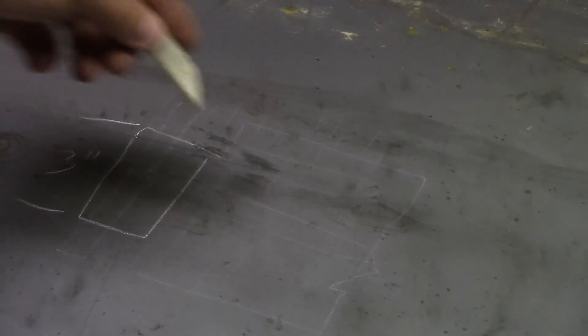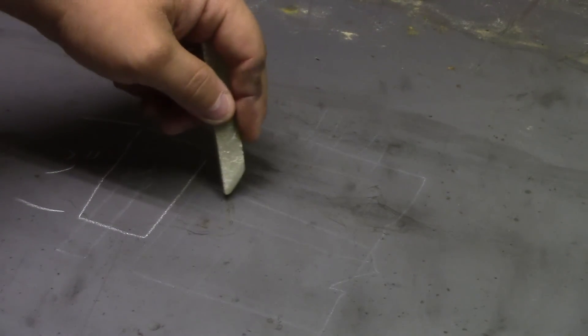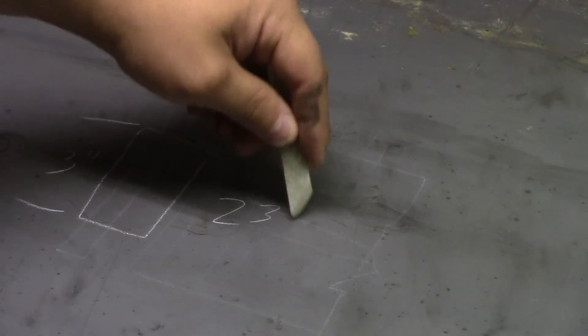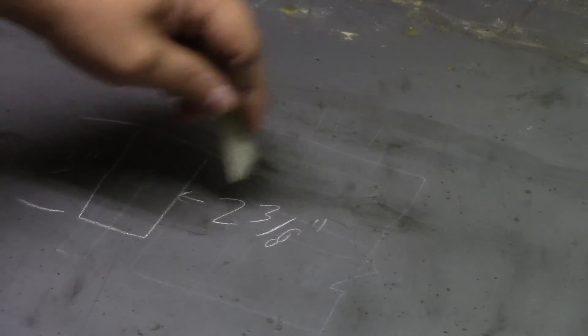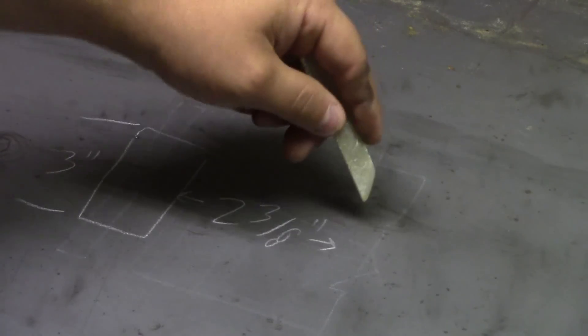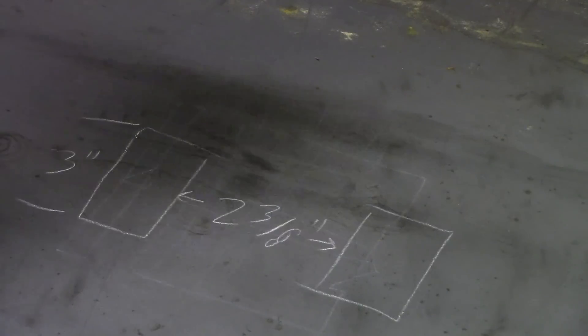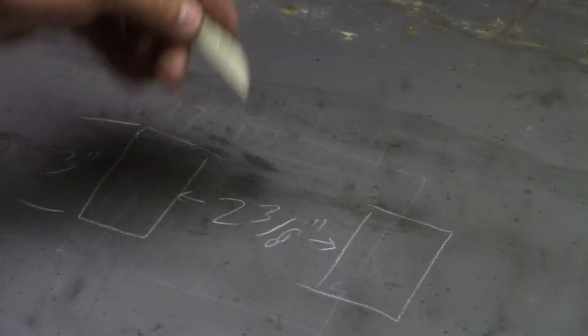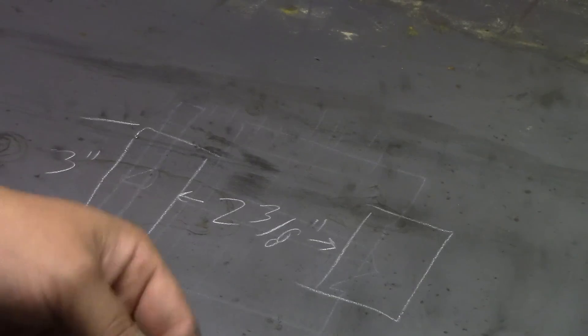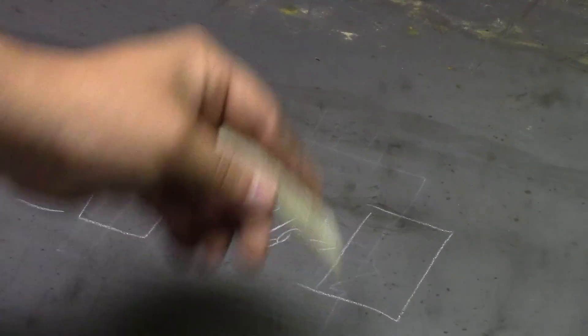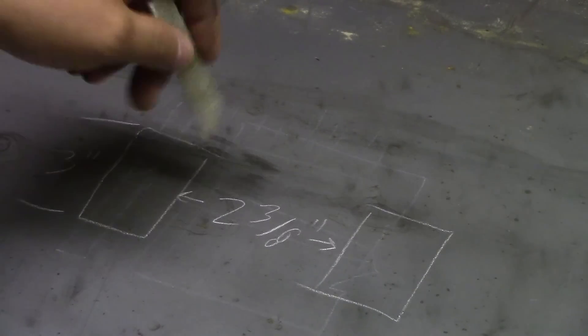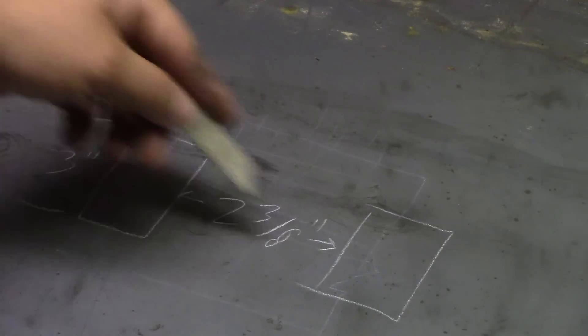From there, you have to have a space in the middle. They've got different dimensions for the yield strength of steel that you're using. So for 50 ksi yield and under, which is pretty much everything that I'm going to do, it's two and three-eighths and then one and a half inch round dies.